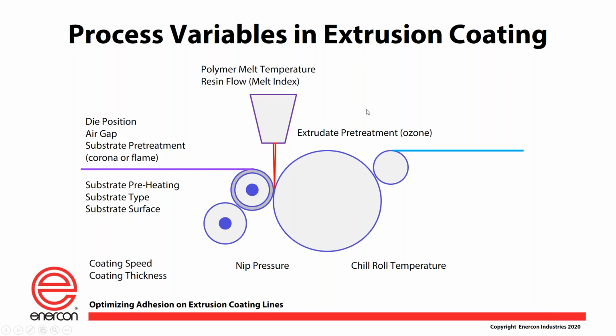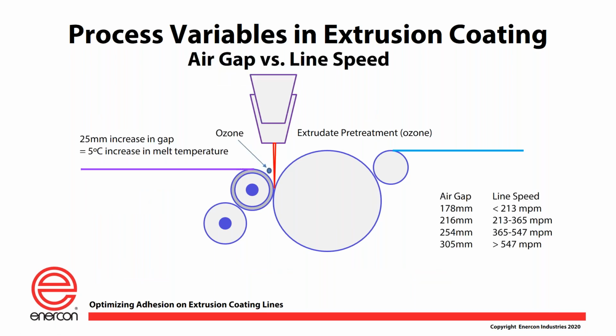Sending ozone into that area can be quite beneficial at not only preventing that from happening, but then giving you all these other benefits. And here's a great example of this, right? So you can see as we change speeds, what we actually can do here relative to the gap between the extruder and the gap where the extrusion meets the primary substrate and where the applicator for the ozone generator is. It can be very, very effective relative to line speed and air gap.